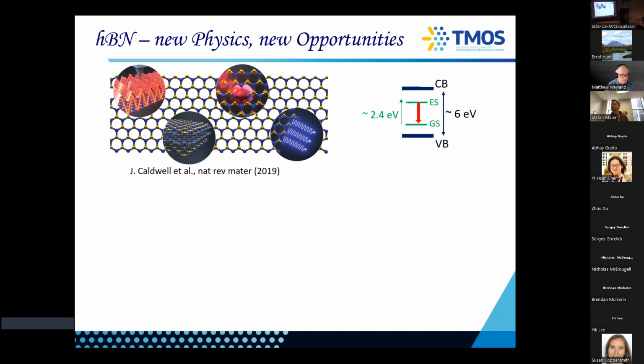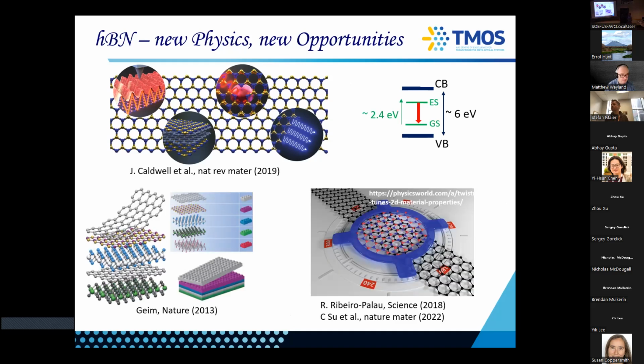But for color centers, it's not actually that important because, I remind you, we don't go from the conduction to the valence band or vice versa. We're really trapping defects very deep within the material. And so there are also more interesting things to do with boron nitride. Obviously, it's a layered material. It's the only wide bandgap material that is also a layered material.